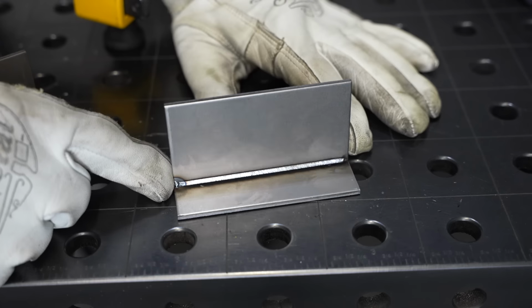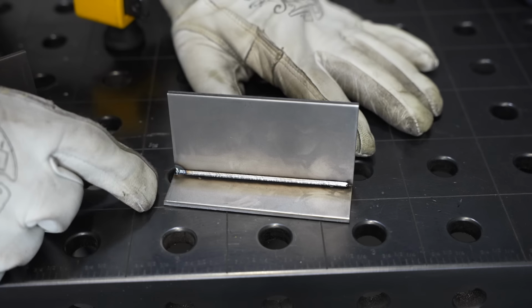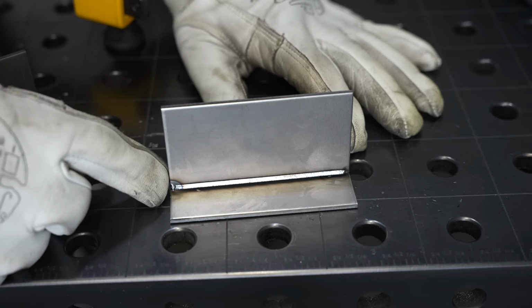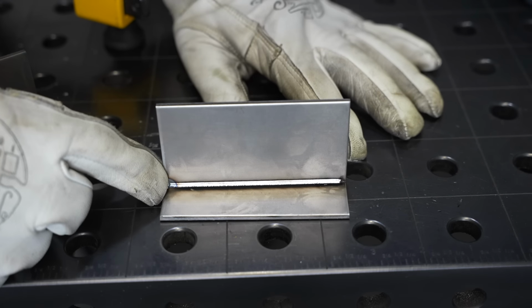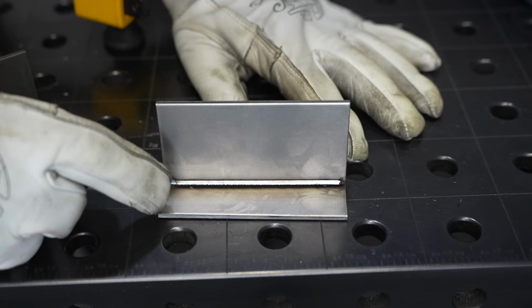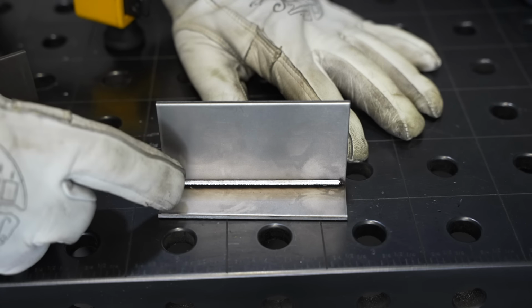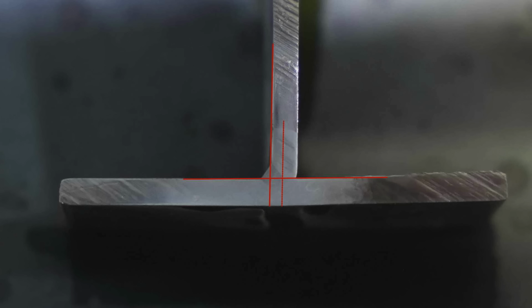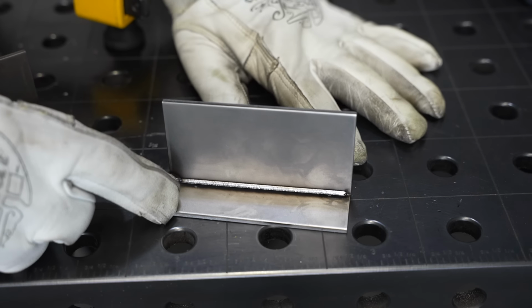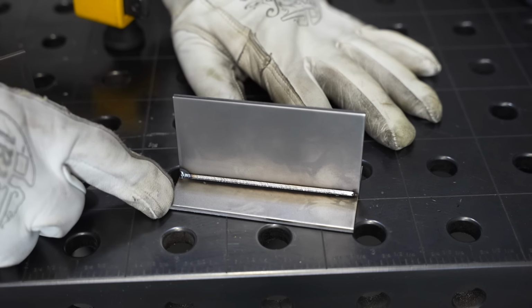All right, look at that slick little bead. I mean, that was easy as it gets, and it's perfectly consistent because it's basically an automatic process. And last week when I took a cross section of one of these welds on 1/8 inch thick material, I found that the penetration was so good that the strength was surprisingly high for this thickness of material.